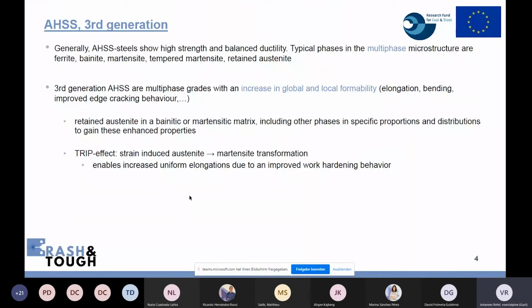And the grades in the third generation AHSS are multi-phase grades with an increase in global and local formability. That means these grades show high elongation values, good bending values, and they have an improved edge cracking behavior. The grades contain retained austenite in a bainitic or martensitic matrix, including other phases, that means soft and harder phases in specific proportions and distributions to gain these enhanced properties. The steels have retained austenite, and this retained austenite enables a TRIP effect. That means we have a strain-induced transformation from austenite to martensite, and this enables an increase in uniform elongations due to an improved work hardening behavior.